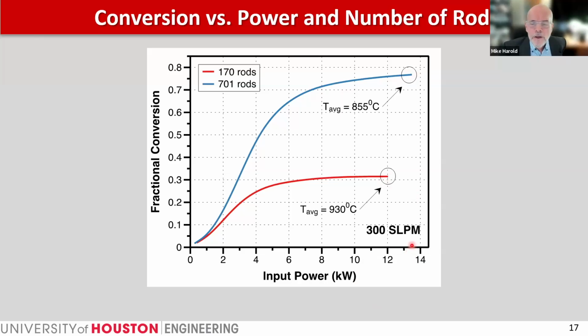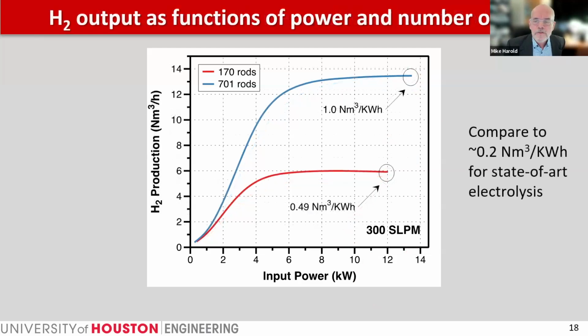Now, I'm showing you a discontinuity here because we cut off the simulation because the wire is getting too hot, and that would lead to a melting of the wire. So that's a self-imposed constraint on these computer experiments. Now, it's interesting to calculate the electrical productivity of the production of hydrogen for the two different densities of rods. And for the 700 rods, we're approaching about 1 cubic meter of hydrogen per kilowatt hour.